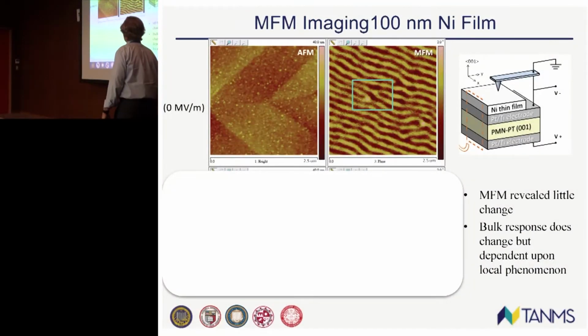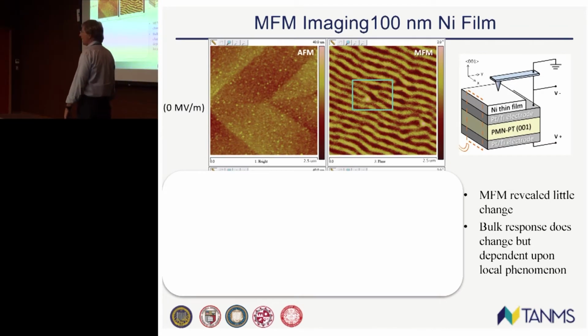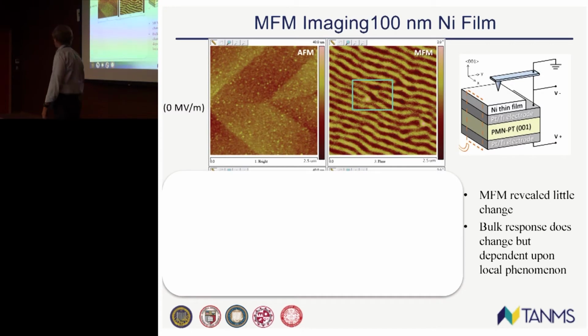Well, let's try this. We're going to do this on a 100 nanometer thick nickel film. The figure on your left is an atomic force microscope image. The figure on your right is a magnetic force microscope image. For those who are unfamiliar with MFM, let's talk about it for a second. These white regions here mean north poles coming out of the material. These black regions here mean south poles coming out of the material. So we actually have striped domain patterns in our film.